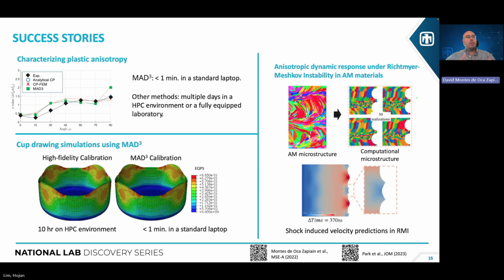I want you to focus on the black squares. As you can see, this material has significant load dependence behavior because we see from 0 to 90, it changes significantly. If you didn't have MAD³, you would need to perform these physical experiments, and as I mentioned before, you would need to have a lab, subject matter experts. But with MAD³, focus now on the green squares, you're able to obtain a similar trend, but you were able to obtain it in less than a minute using a GUI.